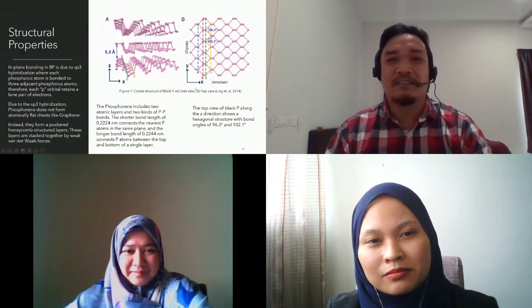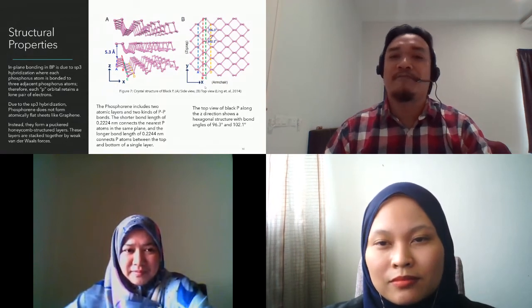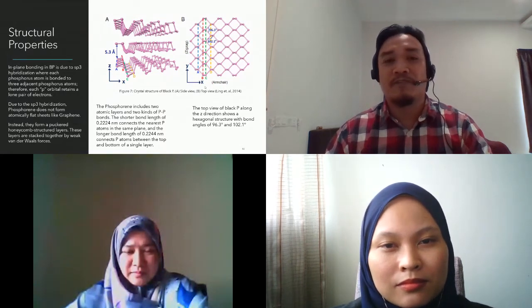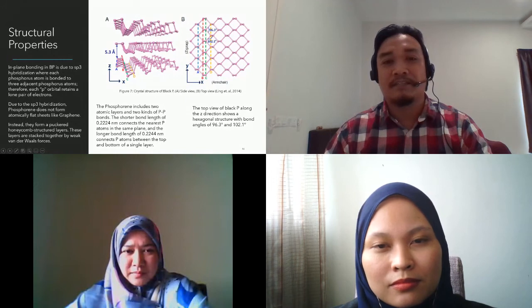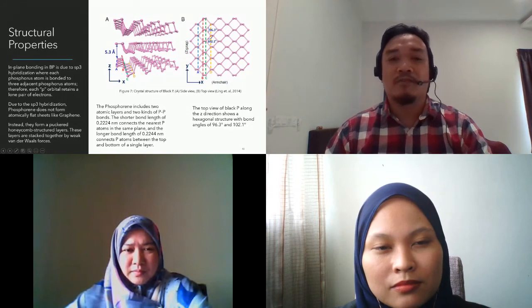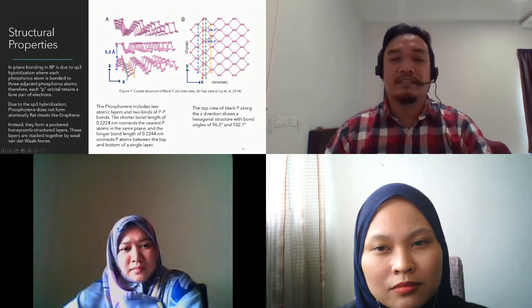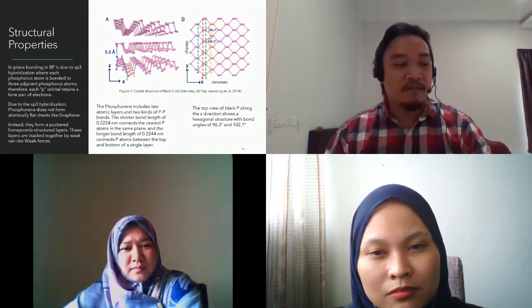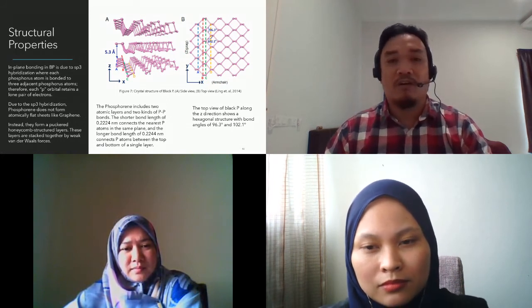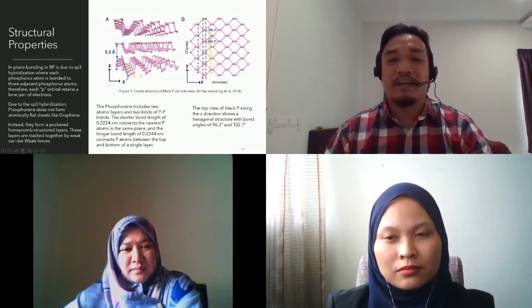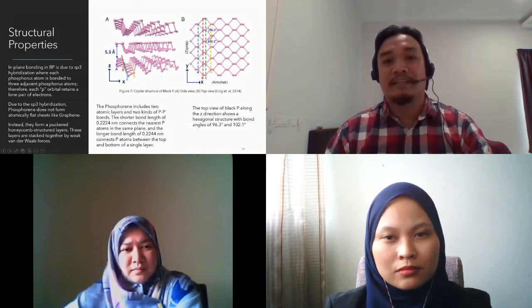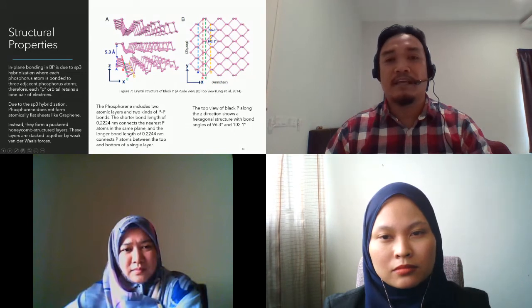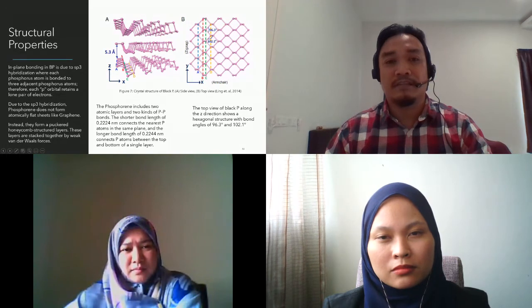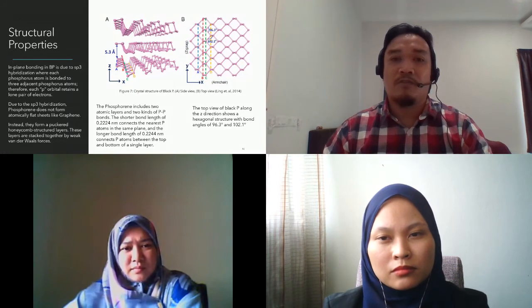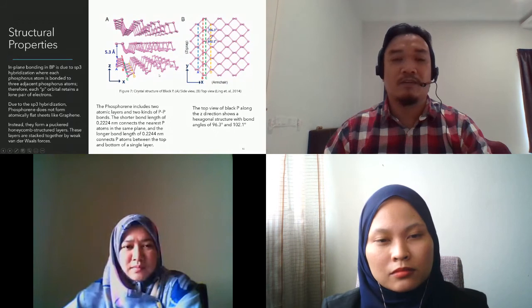Okay, properties of phosphorene. I'll go quickly on this. Structural properties: graphene has a flat surface, but phosphorene has a puckered layer. They have an armchair structure here, so they are quite difficult to agglomerate or aggregate. Like Dr. Huda said just now, nanomaterials tend to aggregate or agglomerate because they have high surface area or high surface energy. But phosphorene has a puckered layer here. Even though the layers stack on each other, they tend to distribute uniformly because of this kind of structure. Difficult to segregate or agglomerate.